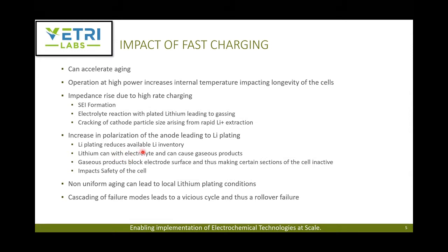So the lithium plating, what will happen is once you plate the lithium, instead of intercalating the lithium into graphite, you don't have the lithium available to be extracted back for the discharge. So as a result, your capacity is impacted. Not only that, the lithium can react with electrolyte and gaseous products, as we discussed earlier in the impedance case. But this also, in addition to the impedance, can block the electrode surface, which in turn increases the polarization of the anode. As you can see, there's a cascading effect.